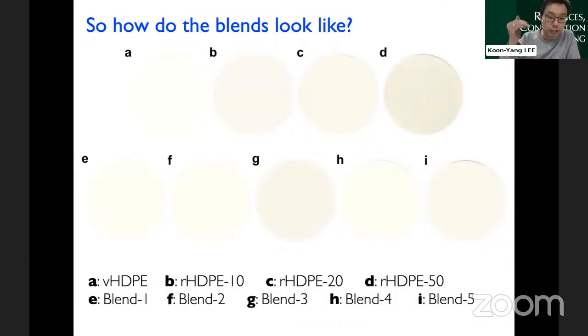And if you look at blend G as well, so these are the ones with virgin polyethylene and polyethylene recycled 50 times, it also has that severe discoloration. But when it comes to blend 4 and blend 5, so these are the ones that are virgin polyethylene mixed with 10 times, 20 times, 50 times recycled polyethylene, there's a bit of discoloration, but not as severe as just purely mixing virgin polyethylene with those recycled 50 times. So there's that consideration there that one should be aware of when you try to mix differently recycled polyethylene into virgin polyethylene, that discoloration that one might want to be aware of.